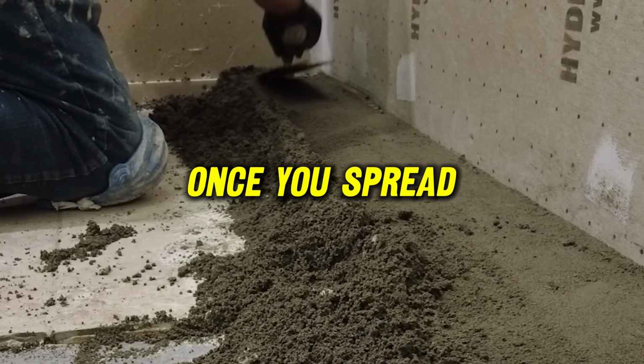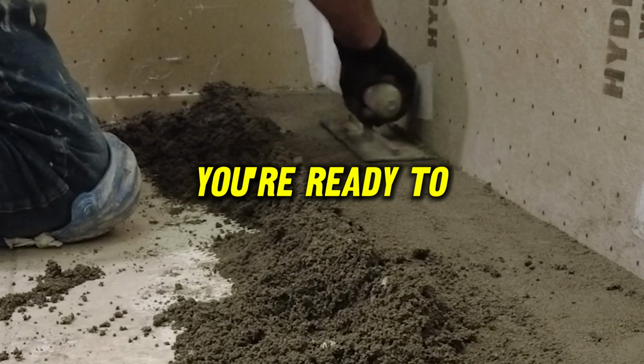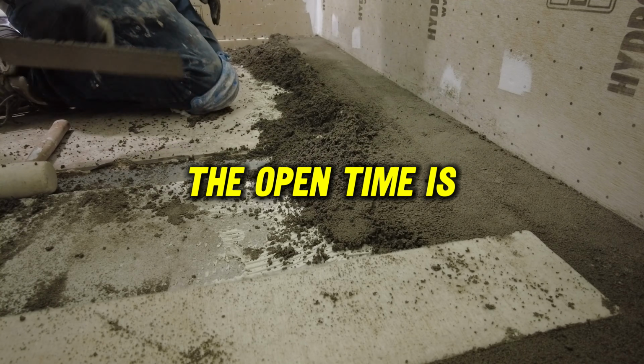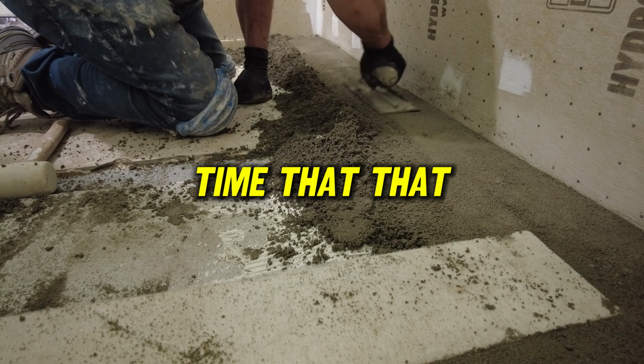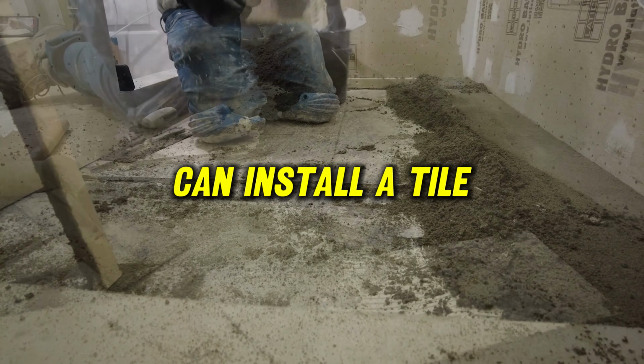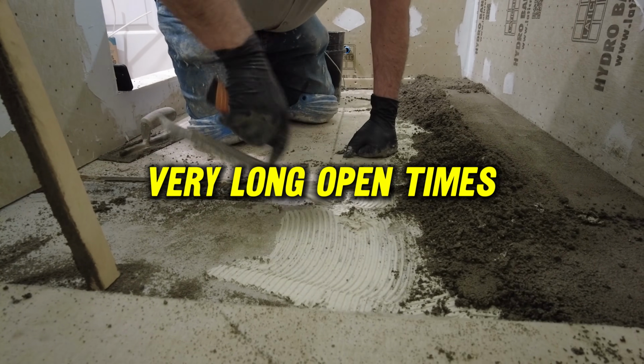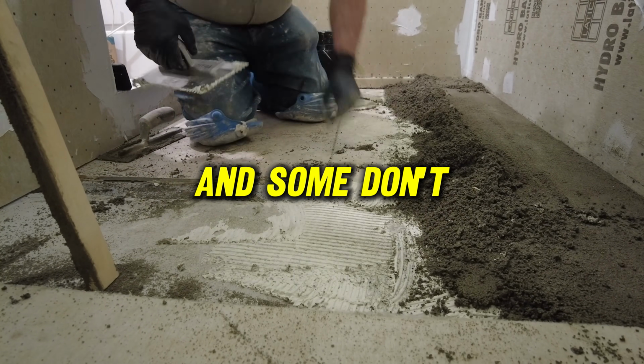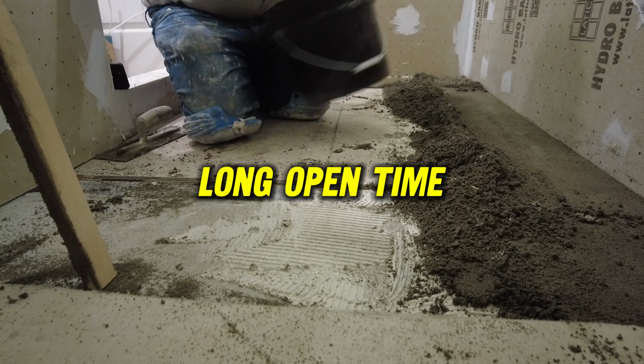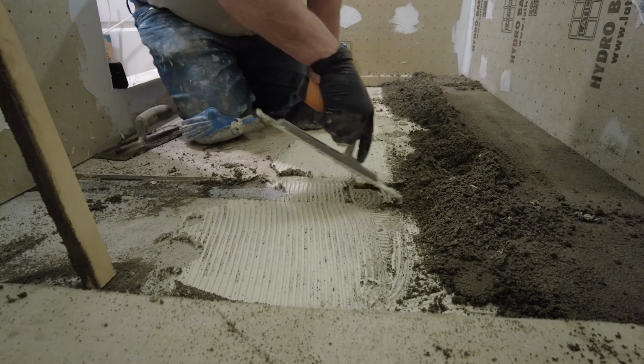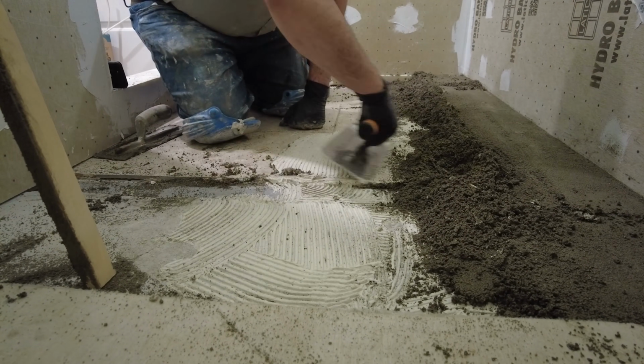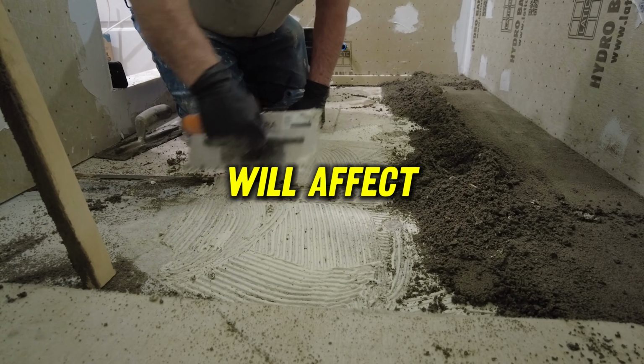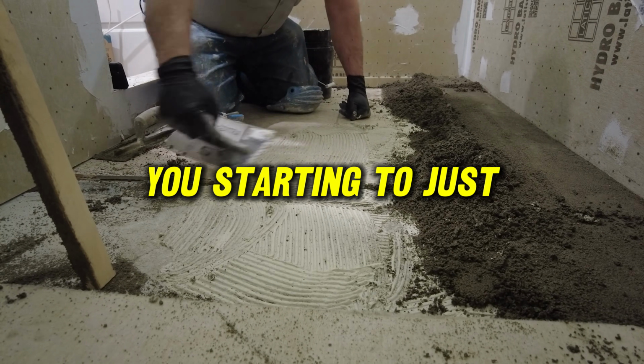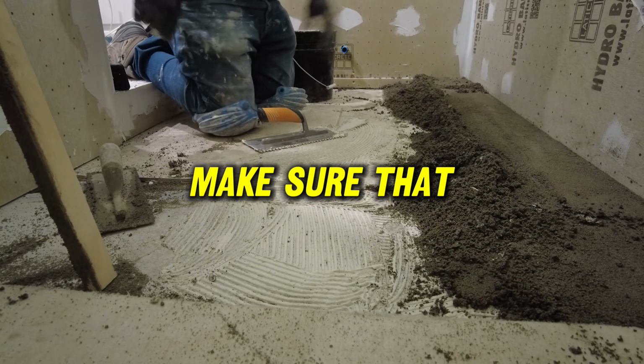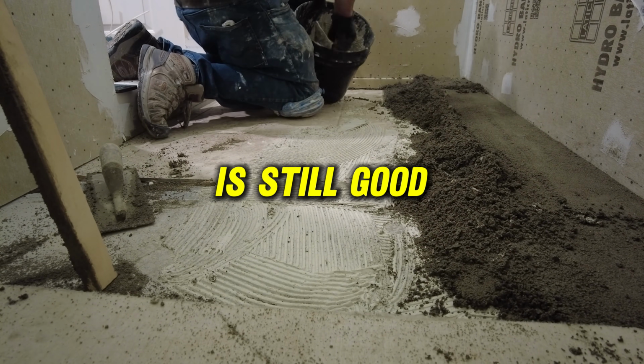Open time is, once you spread the Thinset and you're ready to install your tile, the amount of time that the Thinset will remain tacky and you can install a tile. Thinsets are designed to have very long open times, and some don't have a very long open time. And again, ambient temperature and conditions will affect the open time. If you've spread some Thinset and you've gone a long way and you start to place your tile, make sure that the Thinset is still good.